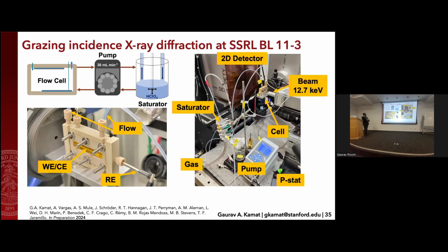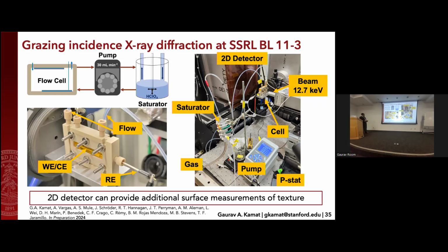So this is what the cell looks like when it's put in. You have this beam that's coming in, you have a cell right there, and you have a two-dimensional XRD detector placed just behind it, and then all of the supporting equipment: a gas saturator, a pump, a gas line and a potentiostat. Just like the experiments we do here in the Stanford lab, we can take this entire setup and move it to the Stanford synchrotron and repeat it in a flow cell in order to look at what's happening on the surface. And this 2D detector is really interesting because it can also provide additional surface measurements for texture. So we can look at what may be happening on the surface.